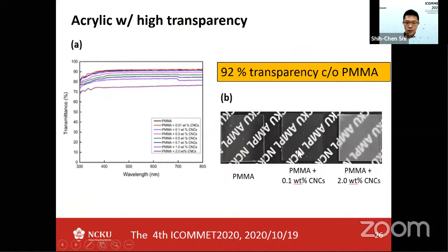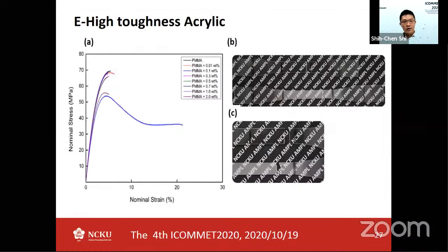Okay, so the transparency is very important, because that is the unique property of acrylic. You can see that with a small amount of CNC additive, the transparency is really high, nearly equal to the PMMA, 92%. So the transparency is no problem. And how about the toughness?